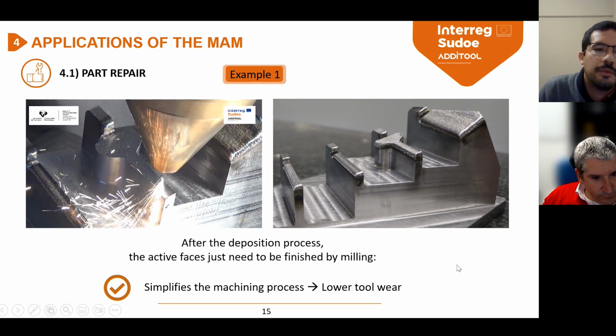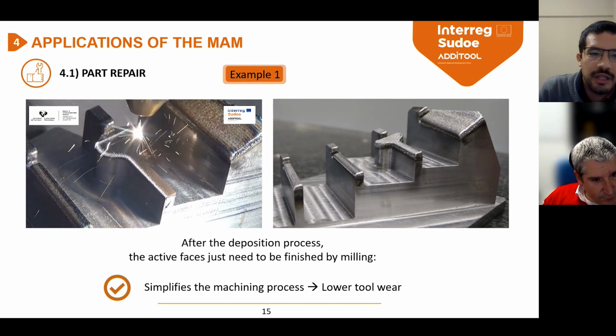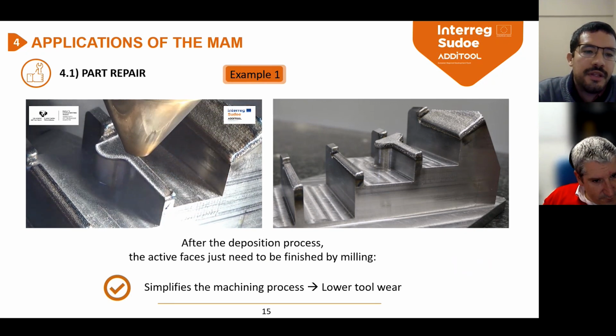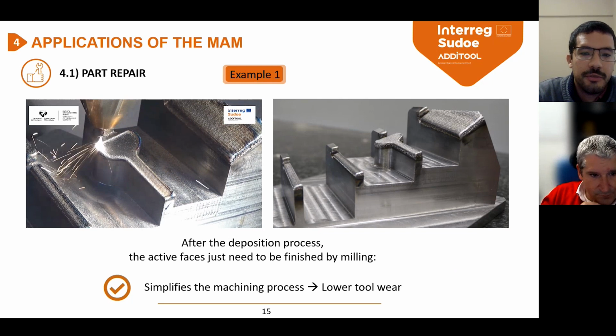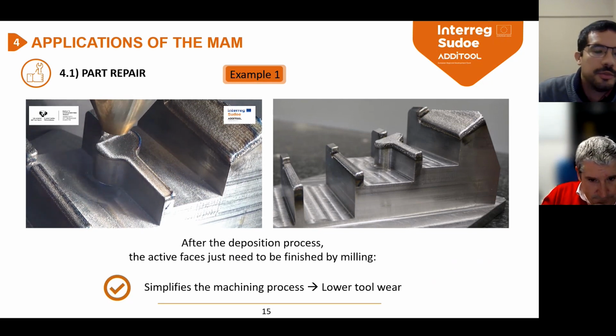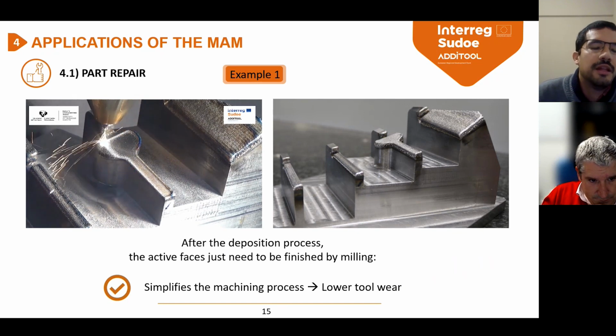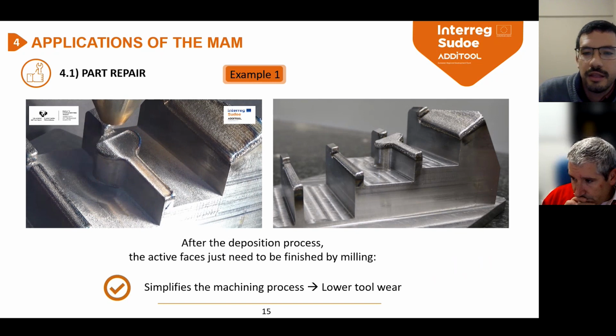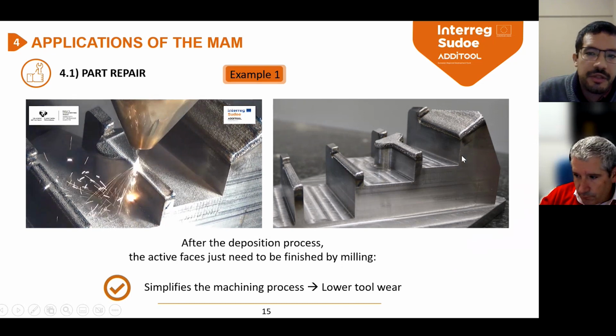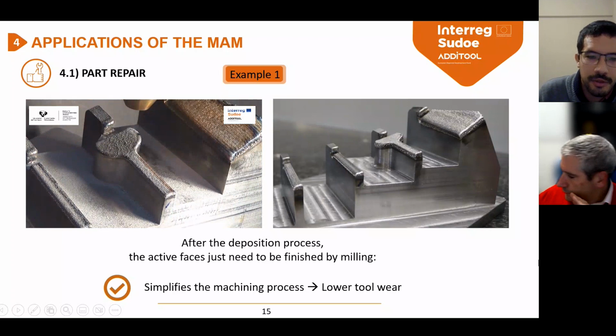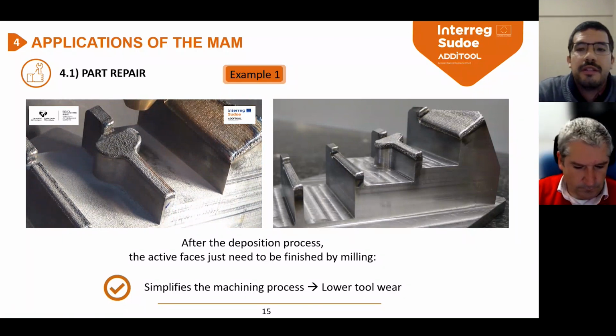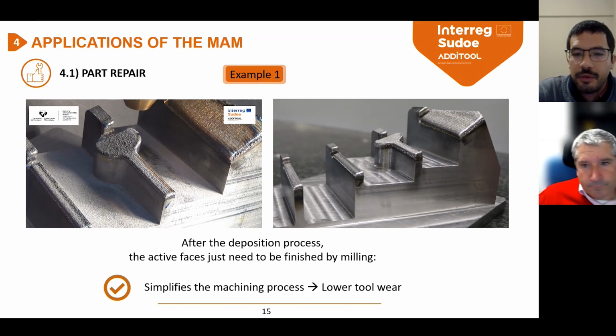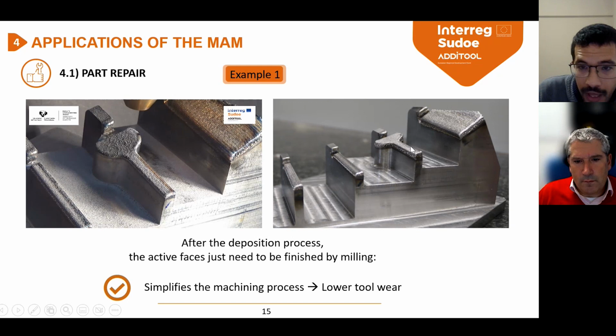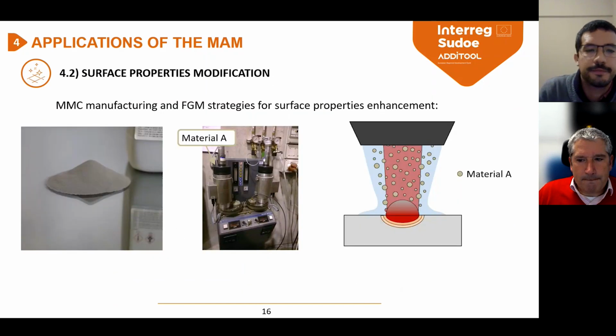Here in this video, you can see how the deposition process works. First of all, we deposit the outer clad, and afterwards, line by line, we fill all the inner geometry. Okay, as I told you before, in order to obtain a layer, and then layer by layer, we deposit the whole height, which in the present case consisted of 3 layers. On the image on the right, you can see the final shape of the repaired tool. One of the main benefits of this strategy is that the final machining process only consists of some small areas, which simplifies the machining process and also lowers the tool wear that it suffers.